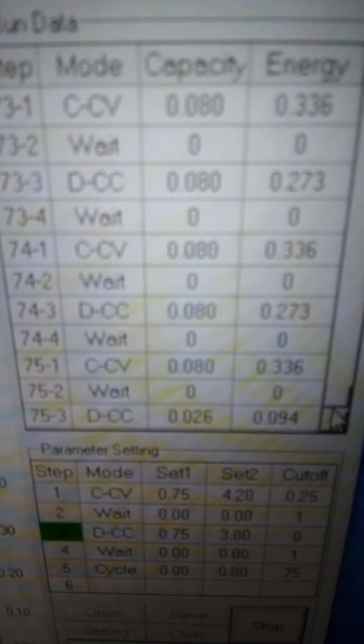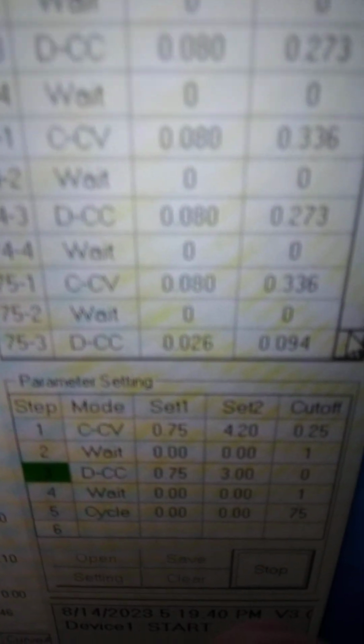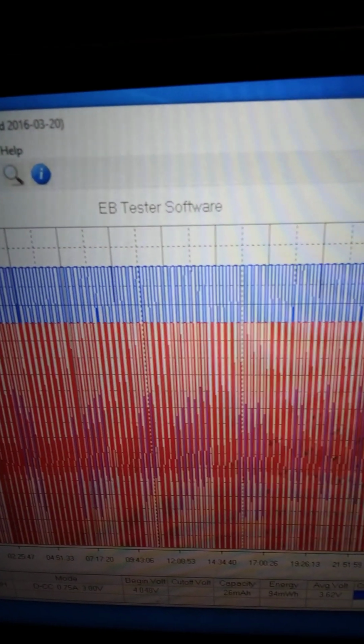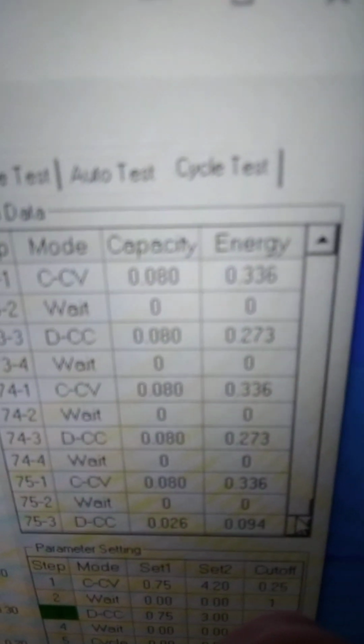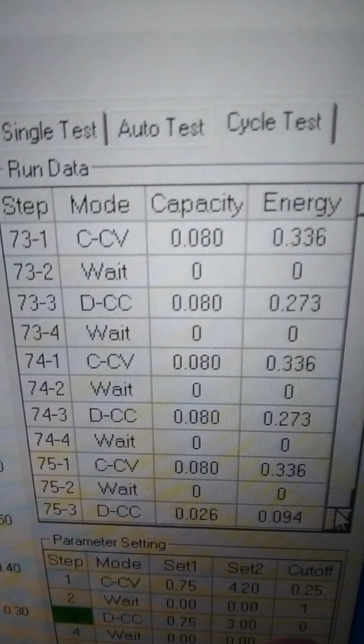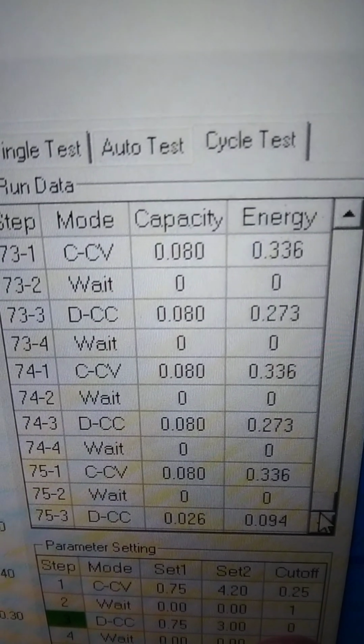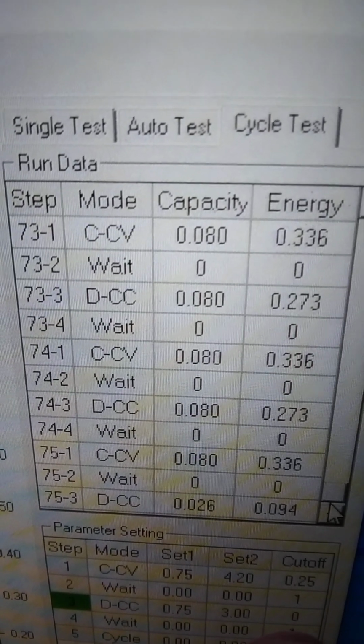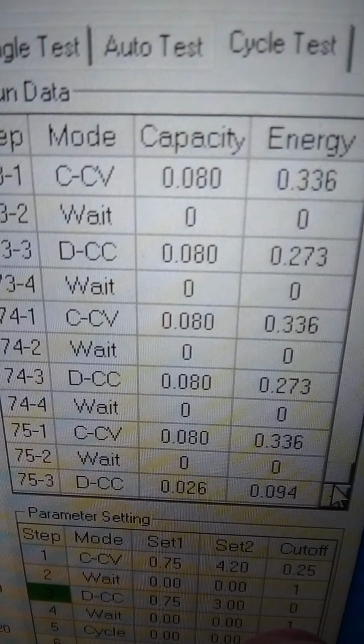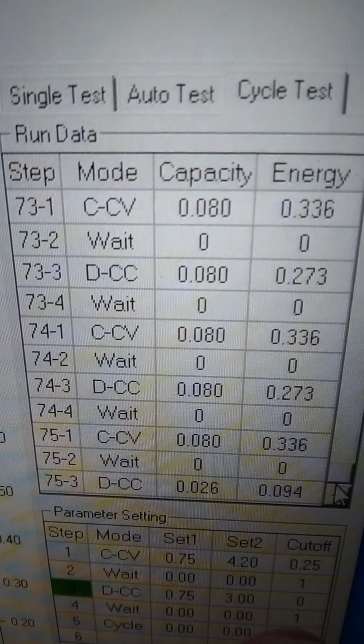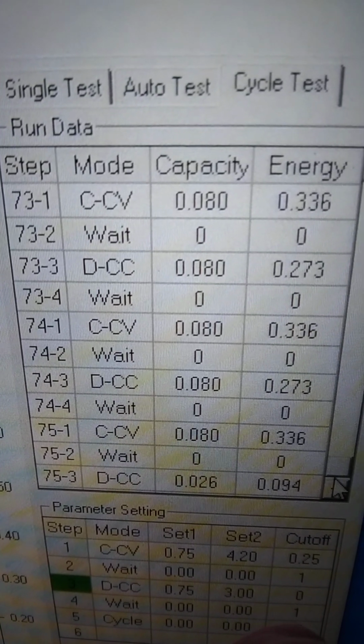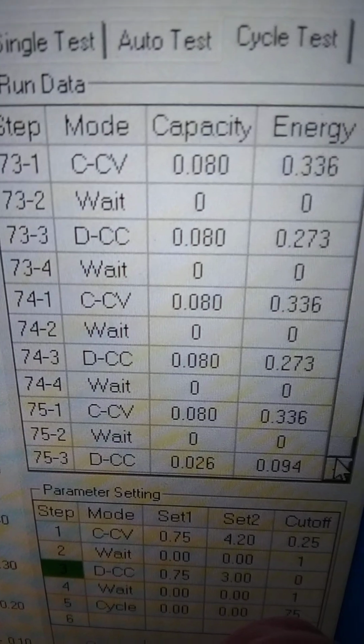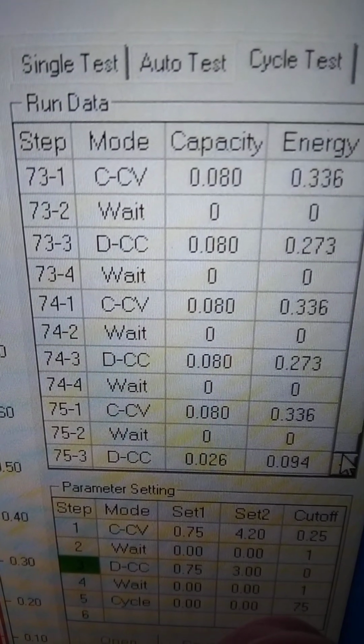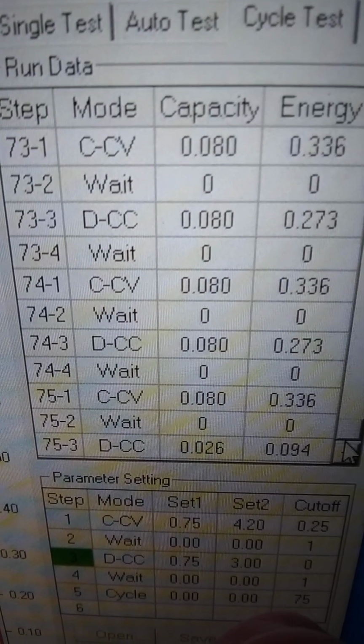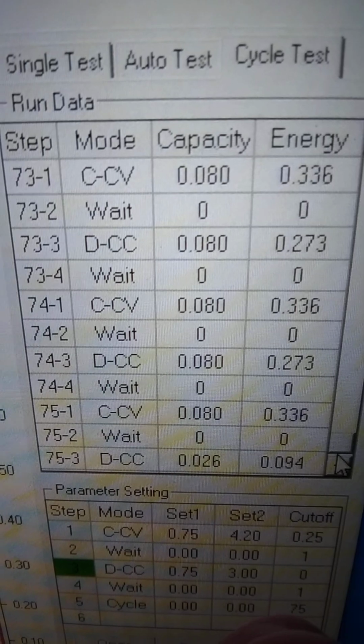The cutoff, 3.00 volts on that lithium ion, and we brought it up to 4.2, and you can see, if I step back, the uniformity of the cycles. And pretty consistent if you look at the capacities for the current, constant voltage with trickle current down to 0.20 amps, and discharge at 750 milliamps to a cutoff of 3.00 volts to protect the lithium ion cell. And we want to just see how the graphite does. Now, I already did a 75 cycle dry circuit, just the graphite section. This is the wet cycle, soaked with electrolyte solution.